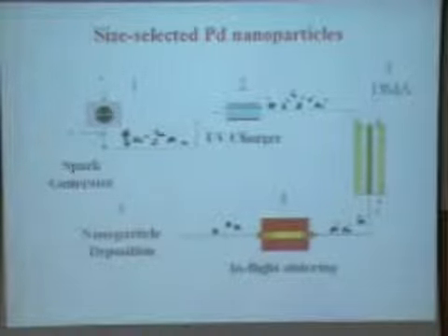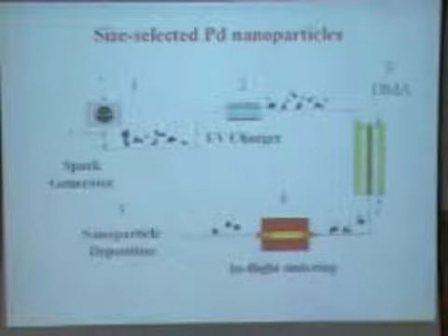And as they come out, they slowly cool down and the liquid, or almost liquid-like phase, is transformed to solid particles. And you can see that we have selected particles of one size. We have made them spherical. We have made them crystalline. This is also very important. And then the gas takes these particles to the deposition chamber where these can be deposited wherever you want to deposit them.